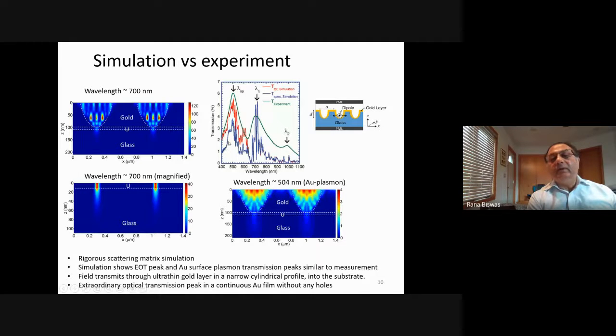And over here, I plot the simulated transmission, the total transmission in red, and the specular transmission in blue. And it compares actually quite well with the experimentally measured transmission. So that's the experiment. And we are sitting at the resonance over here, lambda 1. And the other feature on the right is the surface plasmon of gold. And here the fields are concentrated more at the surface, you see, and not at the bottom of the gold film. So the behavior is, of course, quite different.